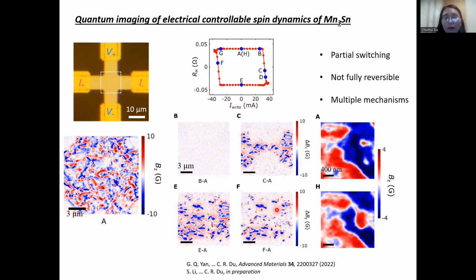And also, if we carefully compare the stray field pattern at point A and also at point H, which is after an entire hysteresis loop going back to zero current, we can see that the stray field pattern doesn't go back to exactly the same configuration. So this suggests that the switching is not fully reversible, and other mechanisms, for instance, Joule heating, may also contribute to the electrically controllable spin dynamics of magnet switching.